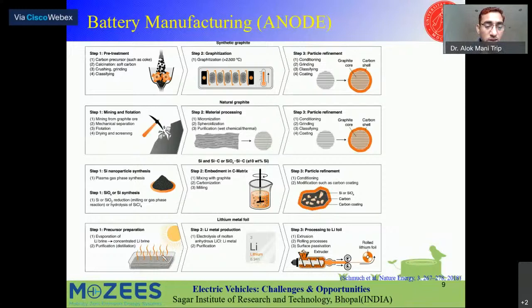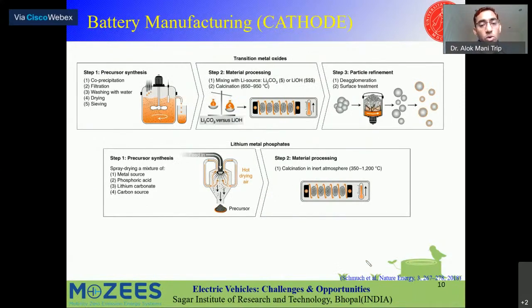Then lithium metal we can use directly. We can clean it and then thin it, and after thinning, thin rolls can be used as an anode. If we go to the cathode side, again we have to synthesize those materials, and synthesis at the bulk stage is still a challenge. All materials which are known at small scale can't necessarily be synthesized at bulk scale, like a kilogram or 2 kilograms, because lots of impurities will come which can create a problem in the cell.